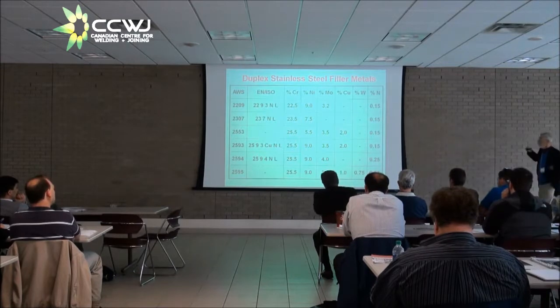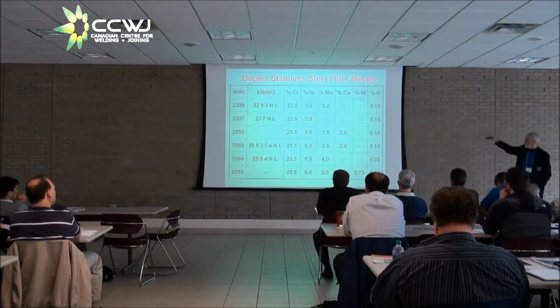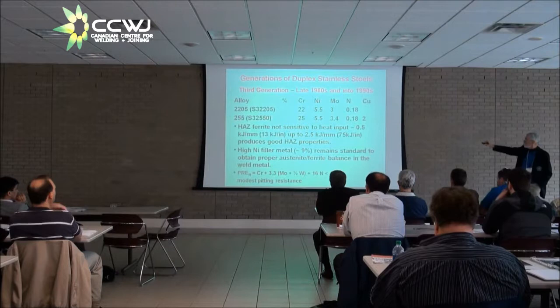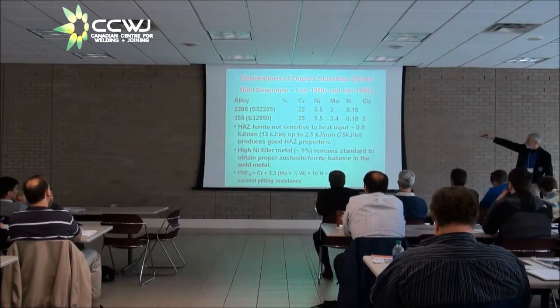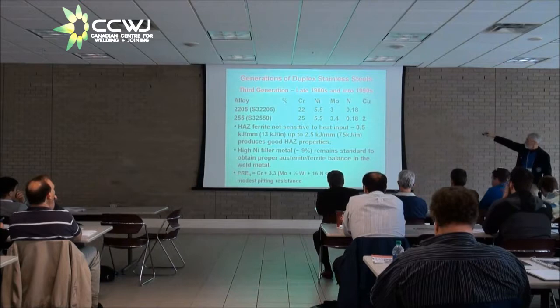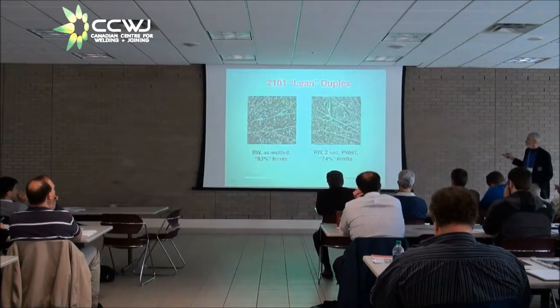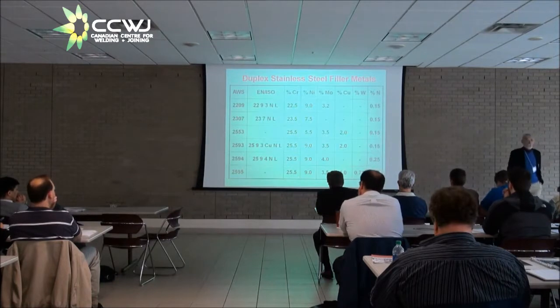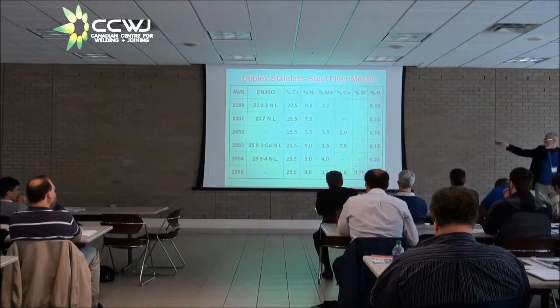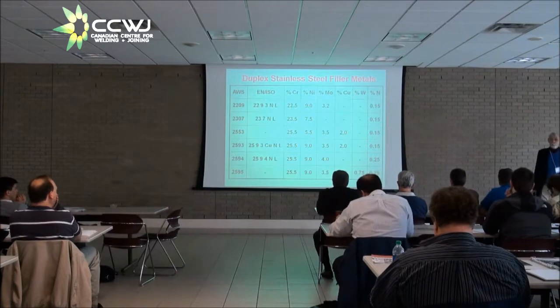2553 exists only in AWS. It doesn't exist in the European or ISO standard. But this is essentially a matching filler material for the Ferralium 255, or alloy 255. This is the wrought composition. Now we go to the filler metal. The 2553 matches that composition exactly. And you would use it primarily on cast material, not on wrought material, because with that low nickel, it's going to have rather poor properties as-welded. When it's annealed, then it has good properties.